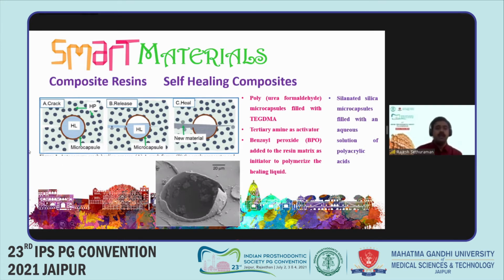As you see in the diagram, a crack starts. The HP is the healing polymer, and HL is the healing liquid. These are already present inside the material. Whenever a crack approaches one such microcapsule, there is a breach, a break. The HL, the healing liquid inside it, gets released. It reacts with the healing polymer and forms a new material that seals that crack, thus making it self-healing. So whenever you choose a composite to be used in areas where high stresses are exhibited, especially post and core restorations, where aesthetics is not much of a consideration, please take such strong composites which have self-healing considerations.